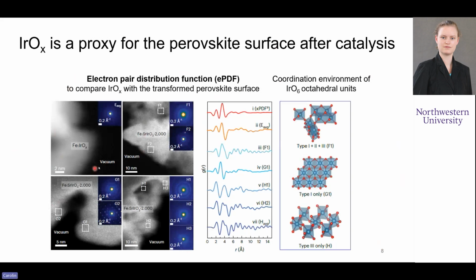And so over here, this panel is our iridium oxide material, and then the other three are different regions of the perovskite after it's been used for catalysis. And then we get the pair distributions out from the local amorphous diffraction patterns. And we can map that in the same way we saw earlier for the X-ray pair distribution function, which we show up here for comparison. And so we find that, again, in our iridium oxide, we have the set of these three types of octahedral connections. And these are also present in some of the regions that we see in the perovskite, like over here. This matches the same type of three different orientations.